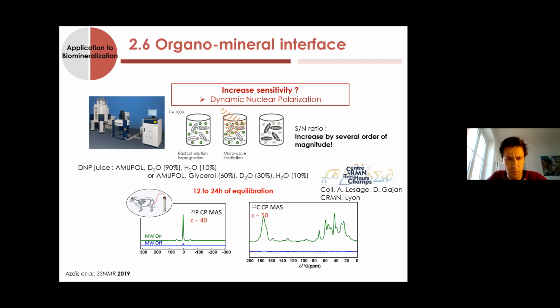To answer that question, it's important to describe the surface of your samples. But the problem is that the quantity of spins and atoms at the surface is very low compared to the bulk, so you don't have much signal. The sensitivity is not so good in that case, so it's difficult to get precision.